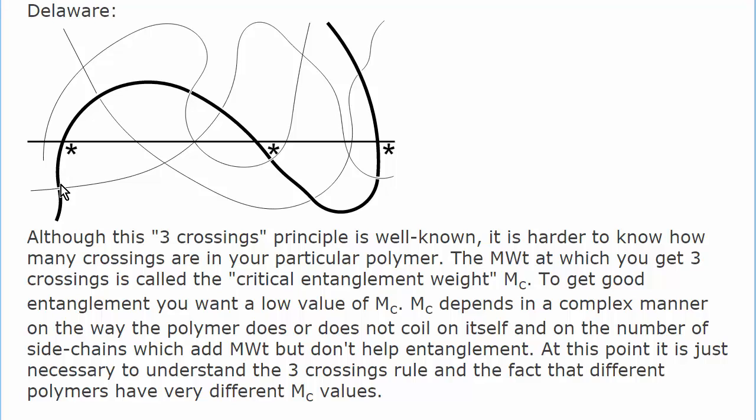An entanglement is shown here. If I have a polymer chain and an interface, if it crosses that interface 3 times, where the stars are, then it's entangled, and if it only crossed 2 times, if you broke the chain here, it would be unentangled. If you broke it here and you pulled up on this point, then it would just pull straight out. If it's not broken here, if it's really like this, if I pull up here, then of course this loop here is going to tangle with something there. It sounds a very simple definition of entanglement. It's a true, really good physics effect.